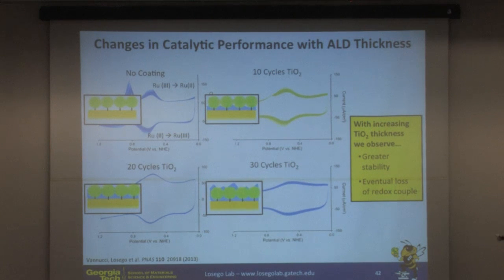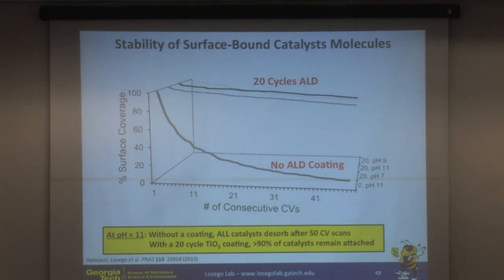However, if we go too thick, 30, 40 cycles, this layer is now about 1.5 to 2 nanometers. These molecules are also about 1.5 to 2 nanometers. So we're actually coating now, our coating has reached the top of the molecule, and we're coating over the molecule. And so for these particular molecules, they're going to lose their activity because we're now no longer able to access the reaction sites for these devices. So we eventually see a loss in our redox couple because we're coating basically the entire molecule.